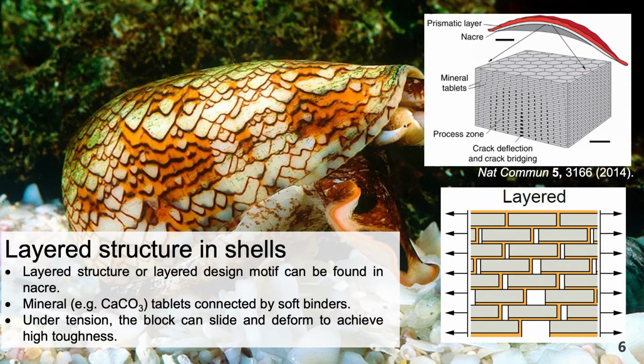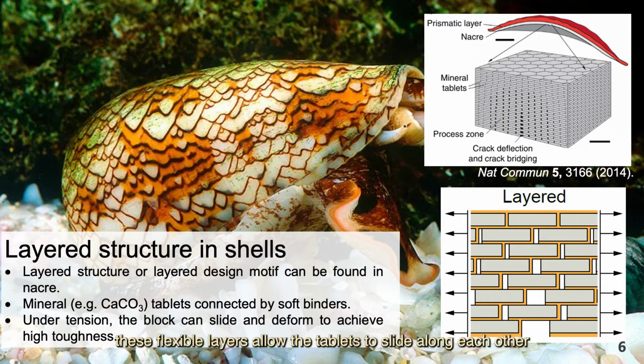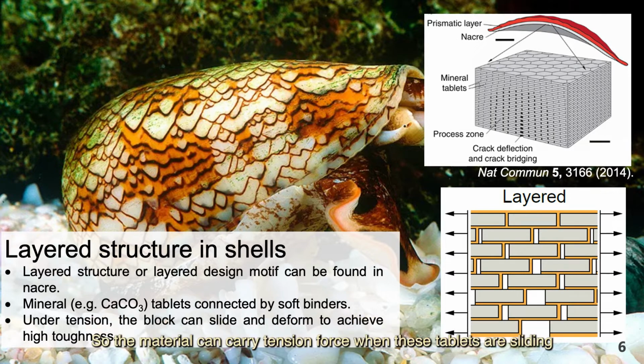The secret lies in the thin layer of flexible biomaterials between those calcium carbonate tablets. When nacre is stretched under tension, these flexible layers allow the tablets to slide along each other. The sliding process generates a strong frictional force without breaking those tablets, so the material can carry tension force when these tablets are sliding.